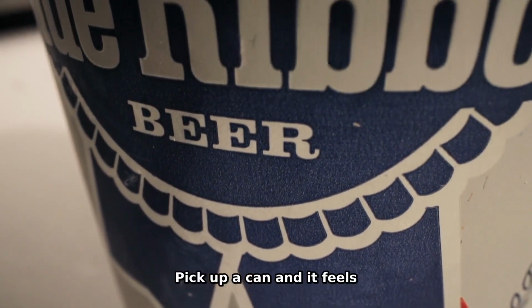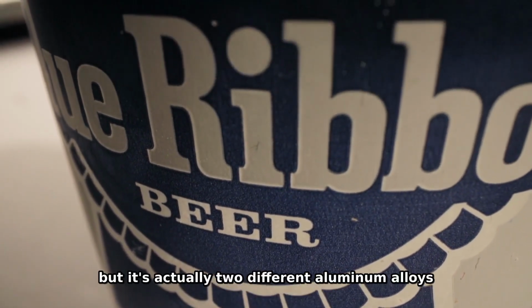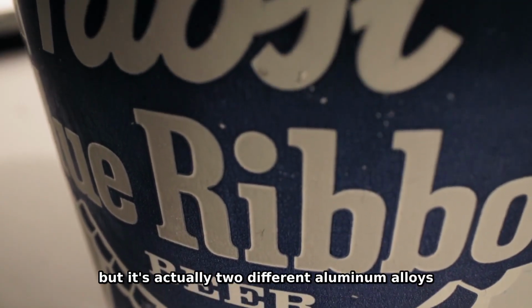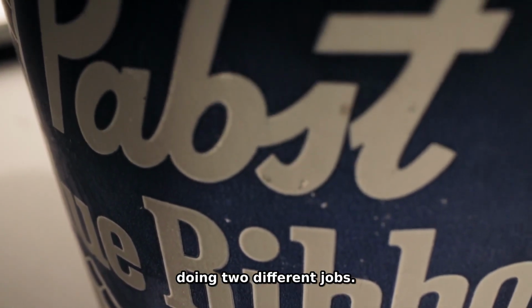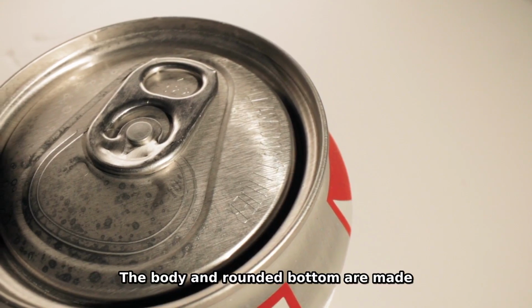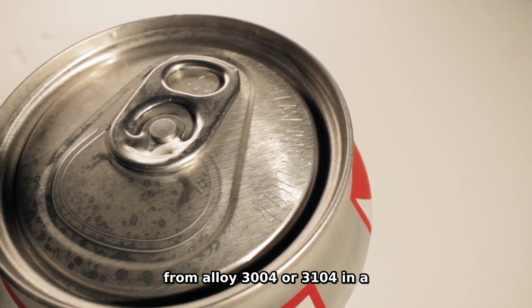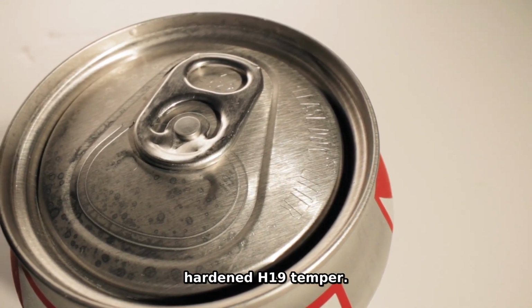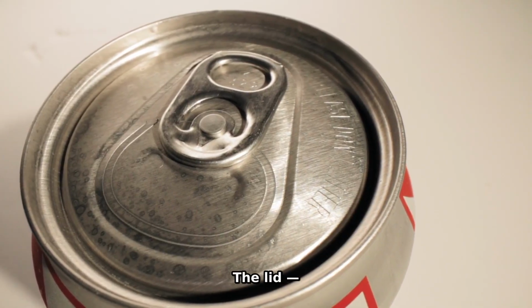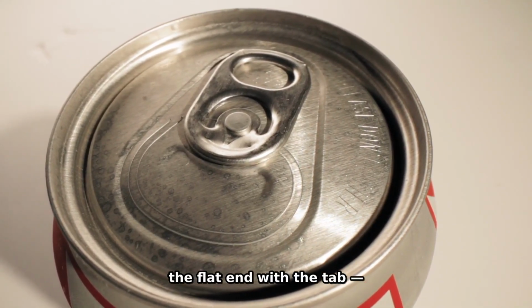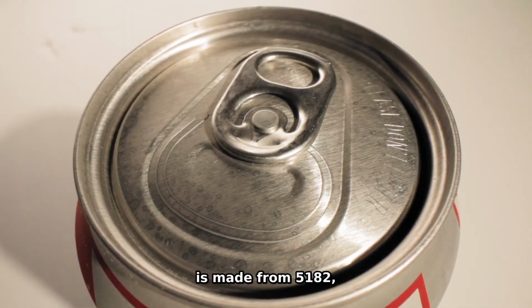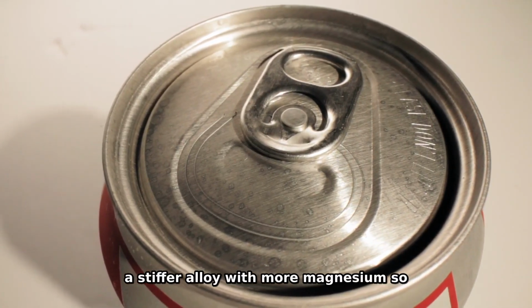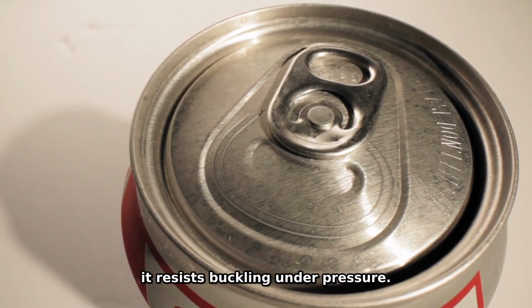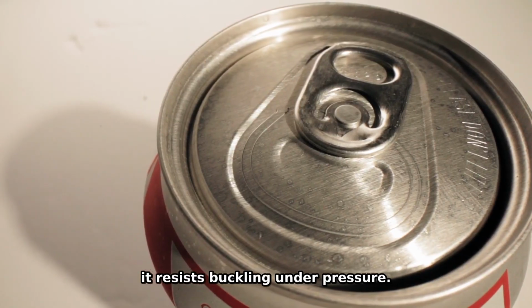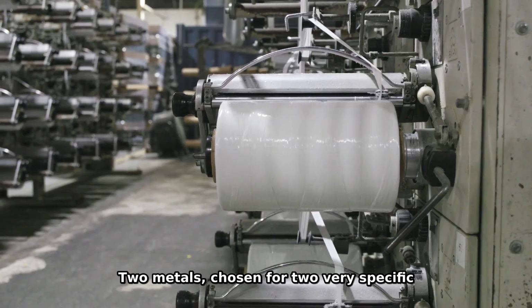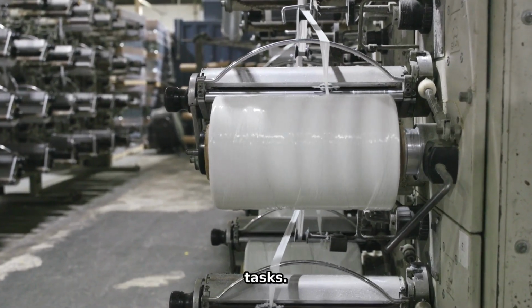Pick up a can, and it feels like a single material, but it's actually two different aluminum alloys doing two different jobs. The body and rounded bottom are made from alloy 3004 or 3104 in a hardened H19 temper. The lid, the flat end with a tab, is made from 5182, a stiffer alloy with more magnesium so it resists buckling under pressure. Two metals, chosen for two very specific tasks.